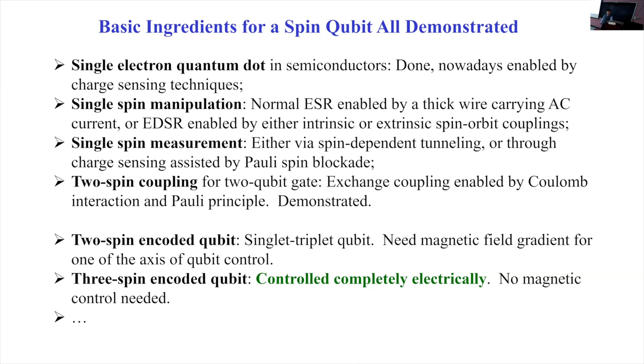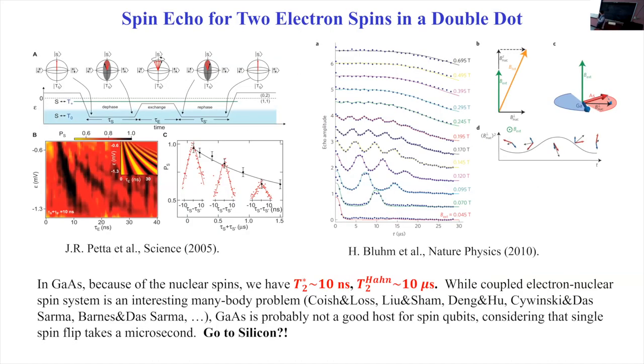Okay. Now, one thing I haven't talked about is the material system. As I mentioned, the original works in spin qubits were mostly done in gallium arsenide. And I think they culminated in these works coming out of Harvard from both Charlie Marcus and Amir Yacoby's groups, looking into two-spin states in a gallium arsenide double quantum dot. This was the first demonstration of both free induction decay and spin echoes for those states, where the coherence time, if you look at it, the T2 star time is pretty short, on the order of 10 nanoseconds or something.